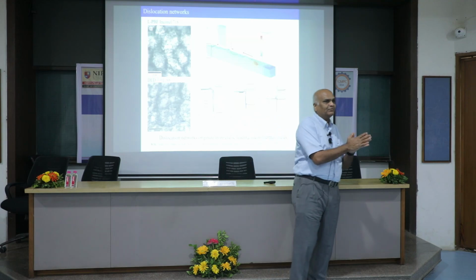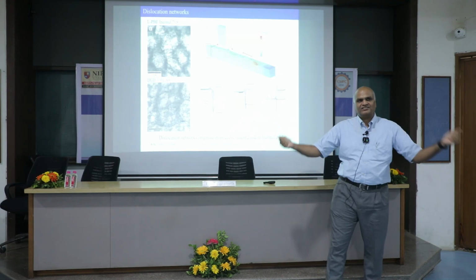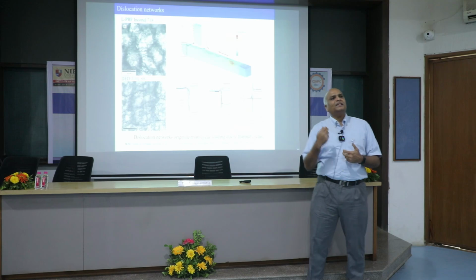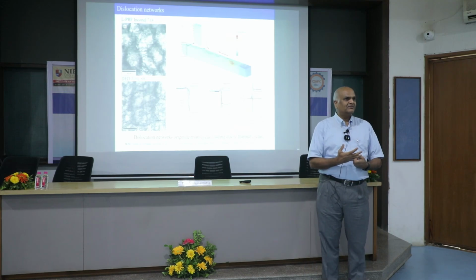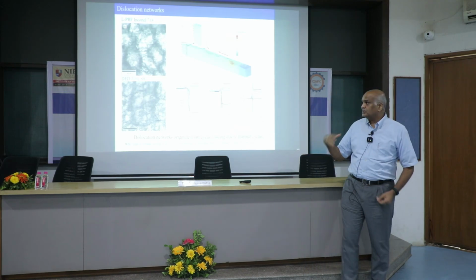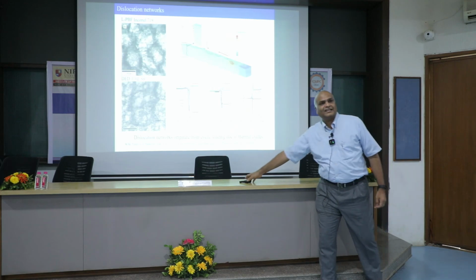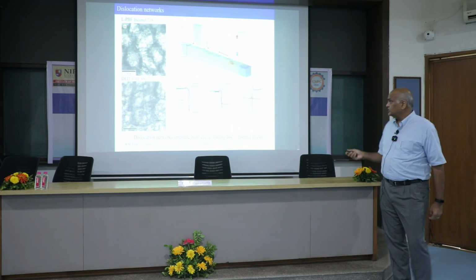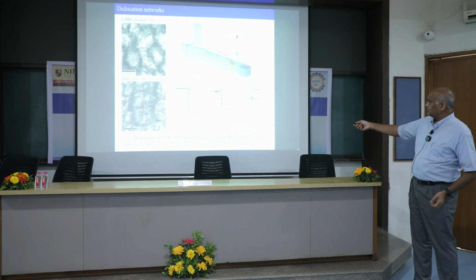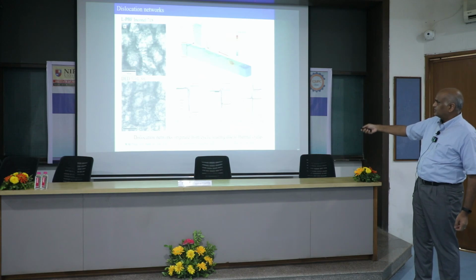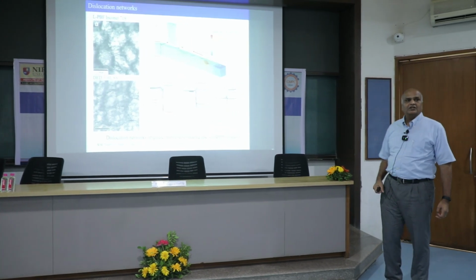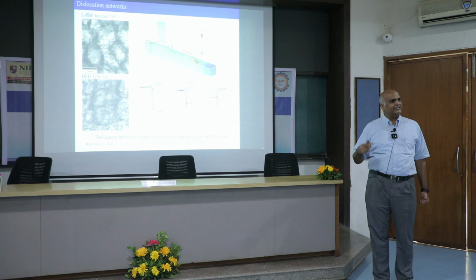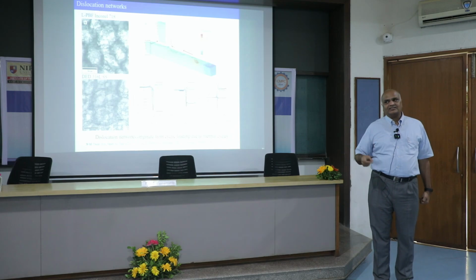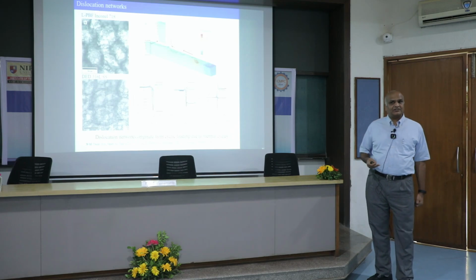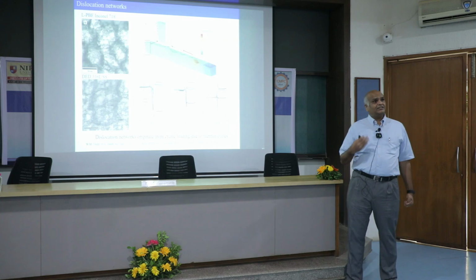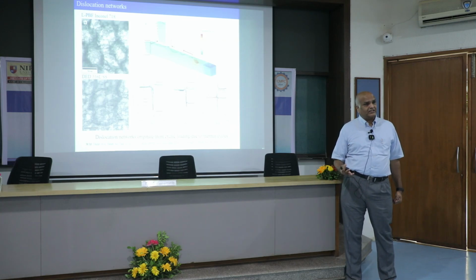So if you take the metal and subject it to plastic straining, fatigue, what we call, you get dislocation accumulation. And that is what happens. Those dislocations accumulate around the cell walls. This simulation tells you that. There are large amounts of cyclic stress fluctuations, plasticity, and as a result, lots of dislocation activity. So you get a large amount of dislocations in the material.